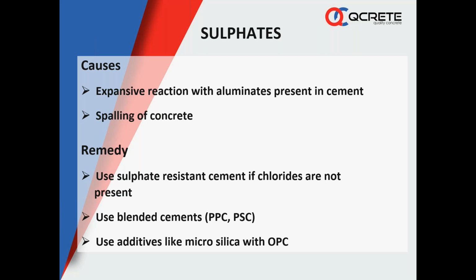So what is the remedy? You have to use sulfate resistant cement. Sulfate resistant cement is nothing but minimizing the C3A, so that the reaction will not take place and your concrete will be safe. But when you are reducing the C3A, suppose in a coastal area like Kerala, for every 100 parts per million of sulfates there are 10,000 parts per million of chlorides. C3A repels the chlorides from entering the concrete. So if you minimize the C3A, all the chlorides can enter your concrete and corrode your steel reinforcement.